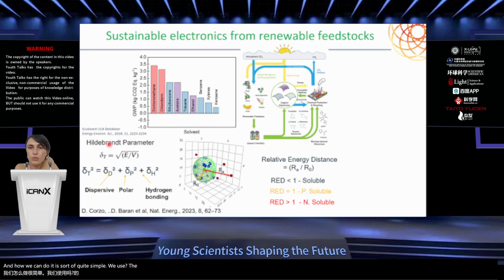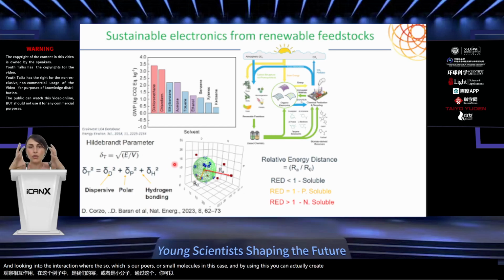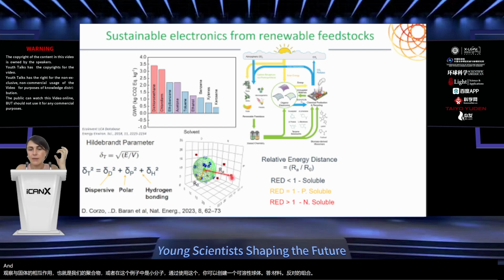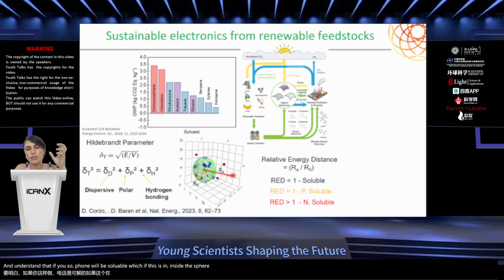We use the Hansen solubility parameter platform to look into dispersive, polar and hydrogen forces of the solvent and look into the interaction with the solid, which is our polymers or small molecules in this case. And by using this, you can actually create a solubility sphere for a material combination and understand whether your solvent will be soluble, if it is inside the sphere, or insoluble if it's outside of the sphere. And this has been an intensive work published in this paper, and you can read more, which is open access as well.